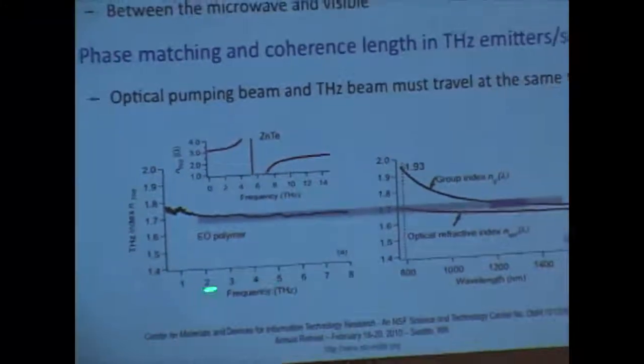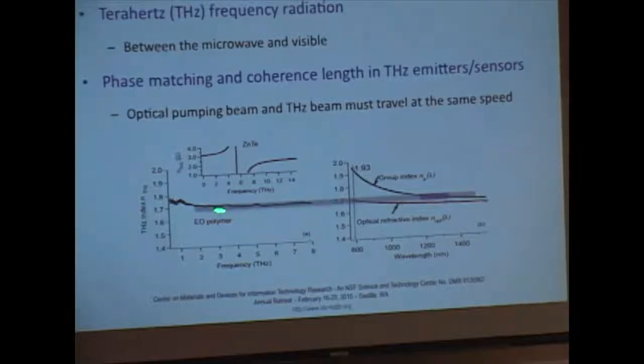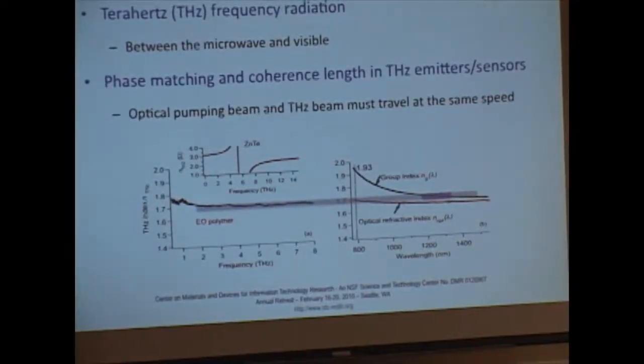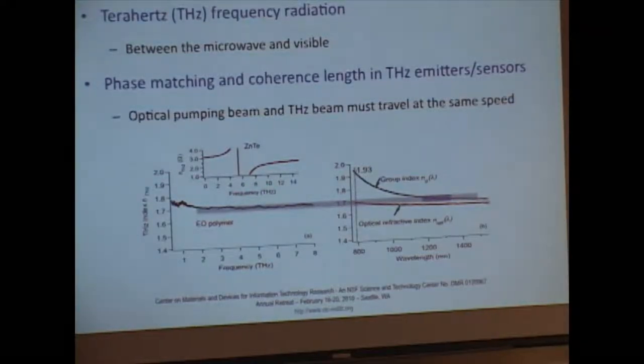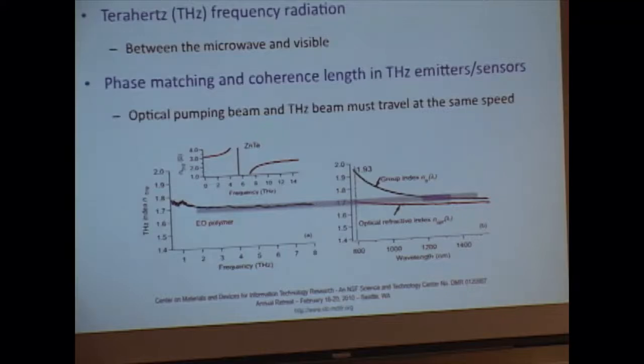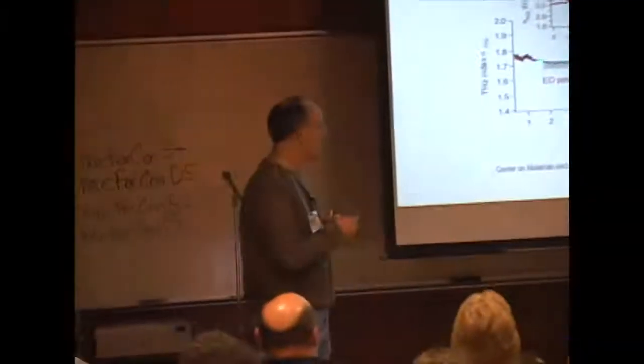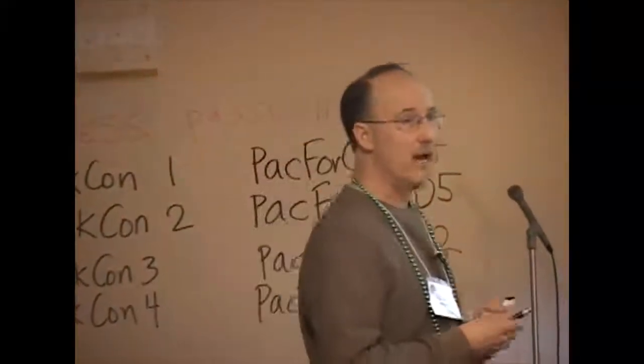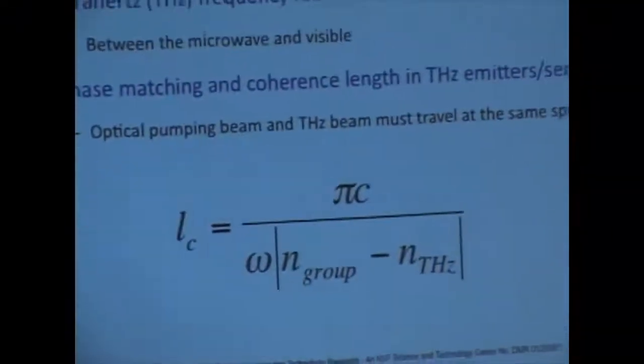It so happens that in the electro-optic polymer systems, we have a sort of fortuitous situation. I'm plotting here the terahertz index of refraction versus the frequency in the terahertz regime. You notice that the index is relatively flat for an EO polymer, and that's to be compared with typical inorganic or any kind of crystalline lattice materials that have this lattice resonance where the index is very different. This gives rise to very poor phase matching, because this phase matching process is really one where we are matching the index of the terahertz wave in the polymer with the group index of the pump beam. Because we're using short pulses, we have to worry about the group index, and so we have to match those two. That's pretty well done in polymer systems. If they are matched, then this denominator is low and the coherence length is large, and then you can use thick materials to generate this radiation coherently.